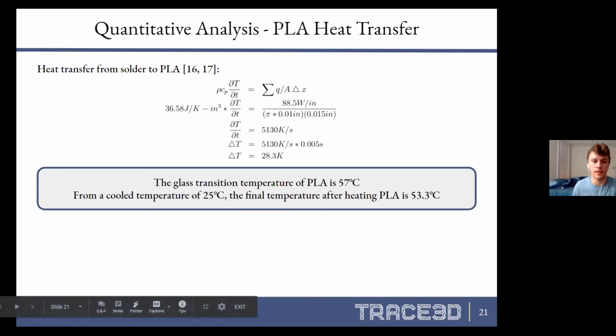On the next slide, we use that result in order to calculate the heat transfer to PLA from the solder. We found a temperature delta of 28.3 Kelvin or Celsius. And starting from the cooled ambient temperature of PLA of 25 degrees Celsius, we found that this temperature would approach the glass transition temperature of PLA, that being 57 degrees Celsius.